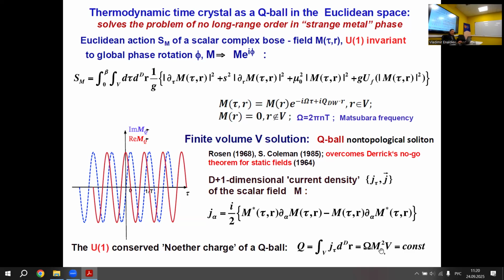What is also important here is that you see the product of omega, but omega is actually temperature, because it's 2 pi times temperature if you take n some integer, for example, 1. So the temperature times the square of the amplitude of the fluctuation times its volume is constant. It means that if we increase volume, the m squared should decrease at constant temperature.